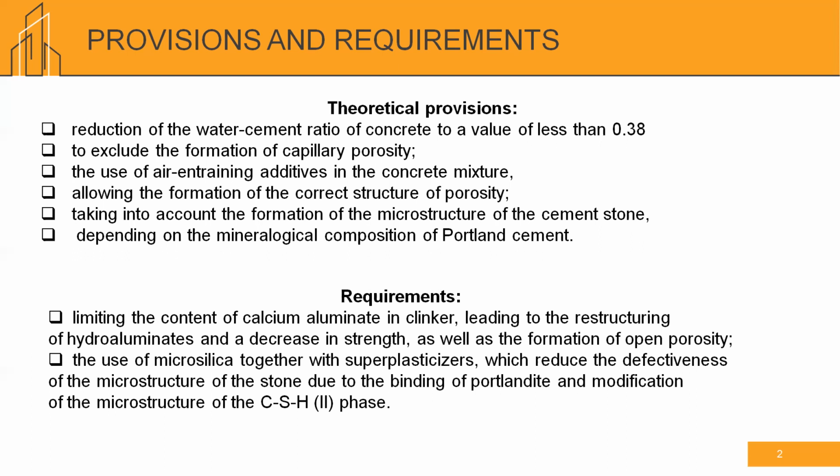As is known, the very structure of calcium hydrosilicate CSH has defects. The data obtained as a result of the experiment can confirm the theory of clogging of pores and defects due to the formation of finely dispersed phases, iron hydroxide, and other ferrihydrite. Coating the pores with finely dispersed ferrihydrite makes it possible to significantly compact the cement stone while increasing its frost resistance. The use of iron salts to increase the density and impermeability of cement stone is known and used in practice.